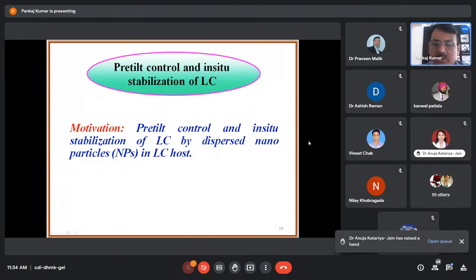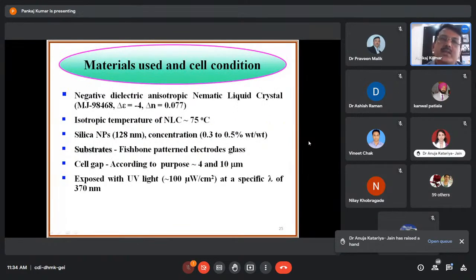the liquid crystal host. So in these experiments, again we have used the nematic liquid crystals of the same anisotropy as well as the same birefringence. The isotropic temperature of nematic LC was the same. Silica nanoparticles, here we have used 128 nanometer, and the concentration we performed was 0.3 to 0.5%. Substrates, that is a very advanced substrate. Here we use the fishbone pattern electrode glass, and fishbone pattern electrode glass is generally used for the wide view angle. So we changed this experiment with the help of the fishbone pattern electrodes.